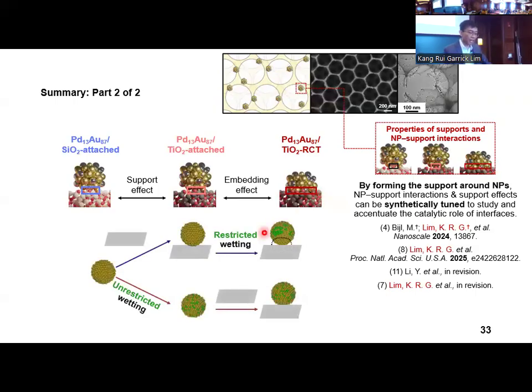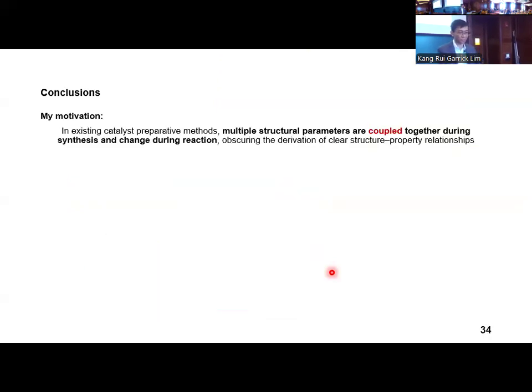Next, we briefly discussed how this nanoparticle support interface can alter the wetting behavior during the reductive overgrowth of a second metal on a nanoparticle host. This results in differences in the secondary metal ensemble size and leads to differences in their spatial distributions on the nanoparticle surface, which directly influences catalytic performance. Taken all together, my work is motivated by the limitations of existing catalyst preparative methods, where multiple structural parameters are coupled together during synthesis and change during reaction.